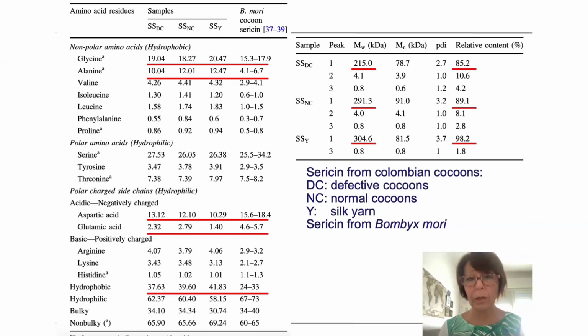We have several opportunities. This is good, but this means that we should be very careful with quality control, because we have different sources of sericin waste, and depending on the source, we can obtain different chemistry. Just looking at some amino acids, for example alanine, we have different content moving from the Bombyx mori cocoon sericin isolated with the standard protocols to the defective cocoon, where you can see it is more than double. If the chemistry changes, the properties will change, and we have different bioactivity. It is more opportunity, but it means quality control.